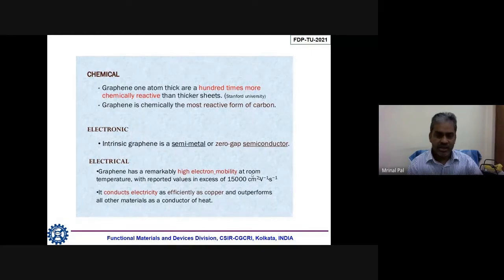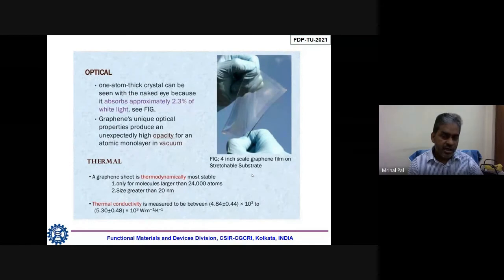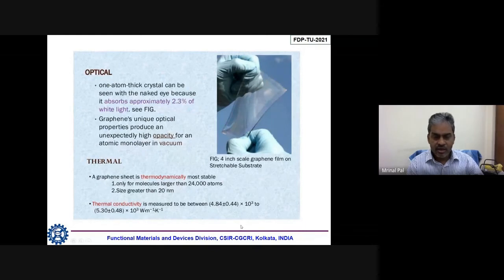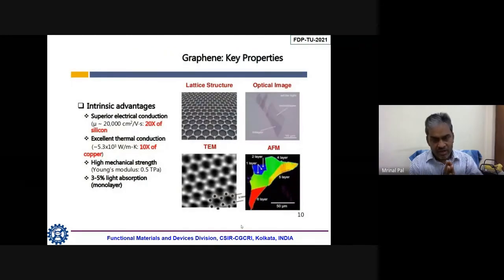So it is very much conducting, its electrical conductivity is very, very high, its thermal conductivity is also very, very high. As far as optical property is concerned, graphene is very much transparent. It absorbs about 2 or 3% of light. So it is very, very transparent, and that's why this is very important for transparent, flexible devices. As this is a single layer, that will be flexible. At the same time, as it passes more than 97% of light, it will be very transparent. So for flexible electronics, this is a very, very important property. Its thermal conductivity is also very, very high, as it is mentioned. You can see that it is more than 10 to the power 3 times higher than a normal thermal conductor. So these are the basic points about graphene, which is different from its bulk counterpart, graphite.